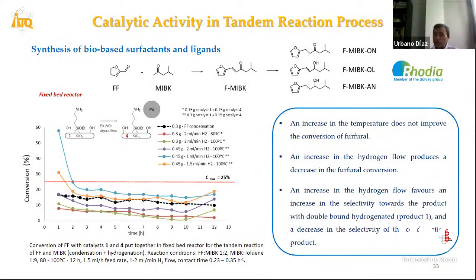Finally, this bifunctional catalyst was effective for a target reaction proposed with Rhodia, another partner of the Multi2HiCat project, to perform a tandem reaction based on the condensation of furfural in the presence of ketones and consecutive hydrogenation to obtain the final products, combining the activity of the base groups and the redox groups. And the results obtained are very satisfactory in a continuous flow reactor.